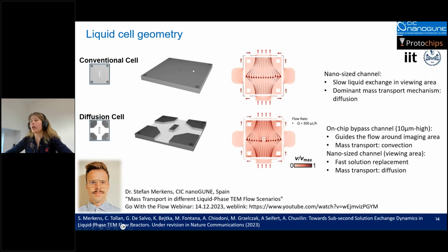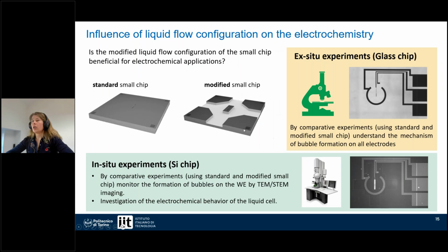than in the conventional cell, and the dominant mass transport mechanism is by diffusion. So basically, it was shown that the new design permits fast solution replacement in the viewing area, and the hydrodynamic properties of the proposed cell were very much improved.